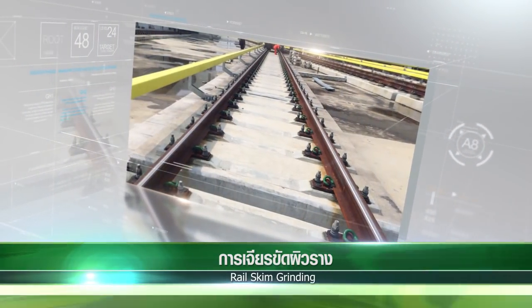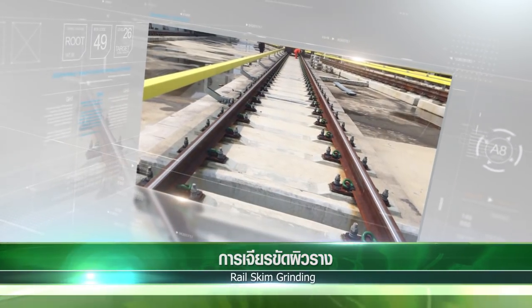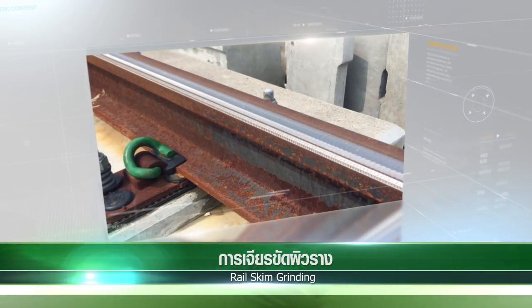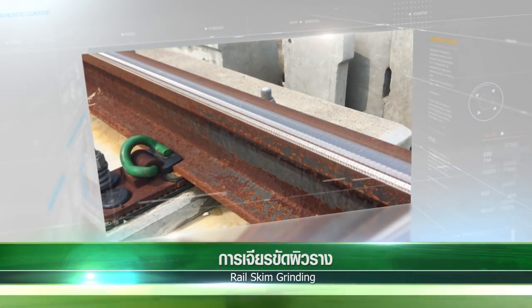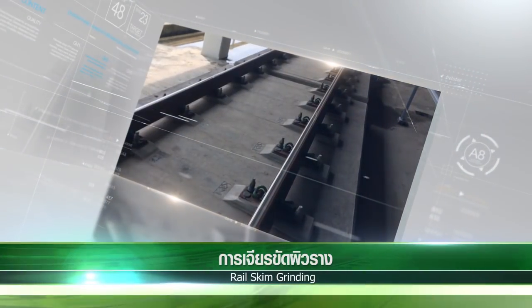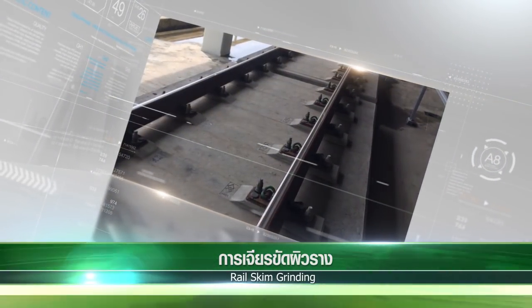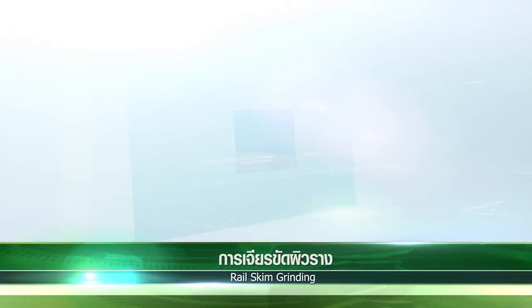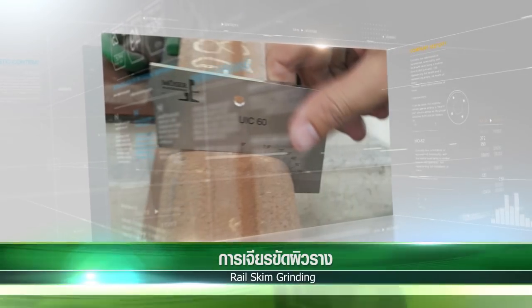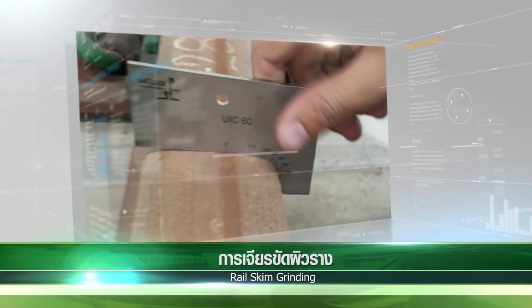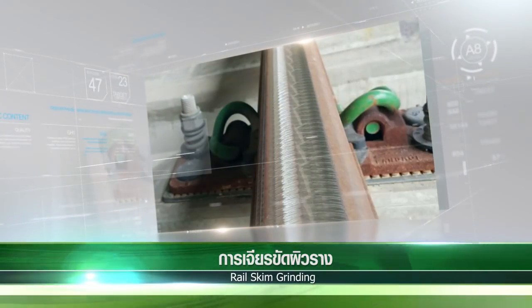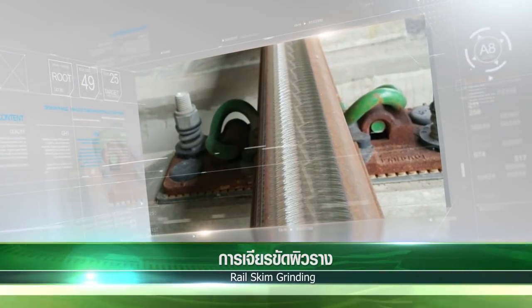A minimum of 5 points per kilometer shall be randomly selected for testing. Visual inspection shall also be performed to ensure that the rail surface is shiny and well finished. There is no gap in any welded joint after each grinding, and the rail surface is even and smooth. In addition, at every 250 meters, the cross-section of the rail must be checked using the UIC 60 E1 rail template to confirm that the rail has developed no excessive deformity after grinding and polishing.